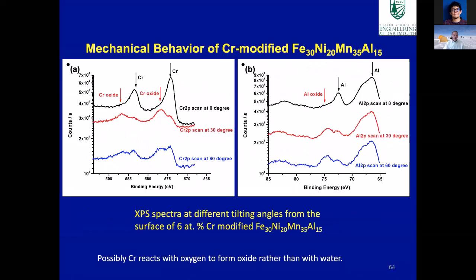Well, we're not wholly sure, but we did some X-ray photoelectron spectroscopy, and the results are shown here. In addition to getting aluminum oxide, we were actually forming chromium oxide on the surface. So the chromium oxide is probably competing with the aluminum oxide for oxygen and actually preventing that hydrogen formation.